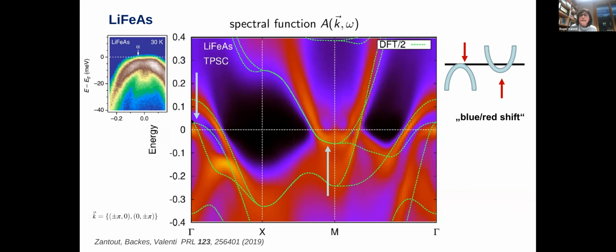And one can see, in fact, indeed, there is this shifting down of the bands at the gamma point and the shifting up towards the Fermi level at the M point. So this blue-red shift is well described by this type of approximation. And the point is that the reason why there is this blue-red shift is because of spin fluctuations at the vectors (0, pi) and (pi, 0). So that the contribution at gamma and the contribution at M are of different signs. And that's why there is this red-blue shift.